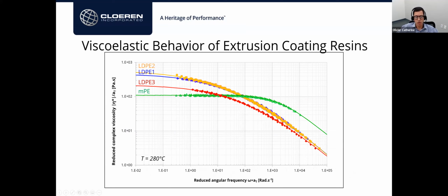LDPE3, which is the material that did show very similar viscoelastic behavior with a slightly delayed crossover point, shows very similar shear thinning at high shear rate or high frequency. But compared to LDPE1 and LDPE2, we see a lower zero shear viscosity, which is understandable and also matches the 16 MI value versus 7. And finally, MPE, the metallocene grade here, shows a very Newtonian behavior and very much in line with the low melt elasticity. And then eventually we see parallel shear thinning behaviors at high frequency.